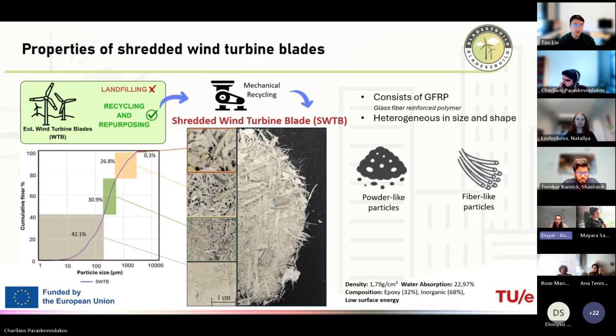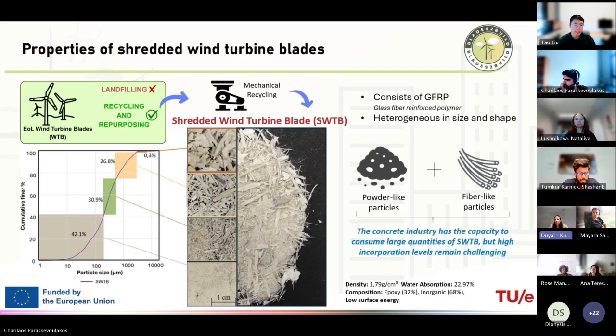So here is a summary. It is a material that consists of glass fiber reinforced polymer, and it has powder-like and fiber-like particles in it. It has a low density and high water absorption, not because the material is hydrophilic. It is actually quite hydrophobic, but the water absorption happens because of the surface irregularities. And it has epoxy and also inorganic content. So the concrete industry has a potential to use this material, either sorting and using it as a reinforcement and replacement for the powder and fiber morphologies. However, high incorporation levels of this very heterogeneous material still remain challenging.